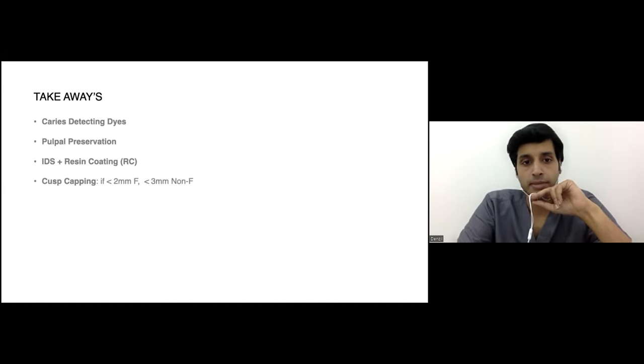Cuspal capping, just to sum it up: the minimum thickness required for functional cusps, that is the lower buccal and the upper palatal, should be 2 millimeters at the base, and 3 millimeters if it's a non-functional cusp, that is the bull concept. There are multiple alternatives to direct composite: indirect composite, semi-direct composite, where a Teflon is also placed and you can just cure it and then additionally cure it extra-orally and then bond it, or ceramic bonded restorations, and fibers for stress reduction.